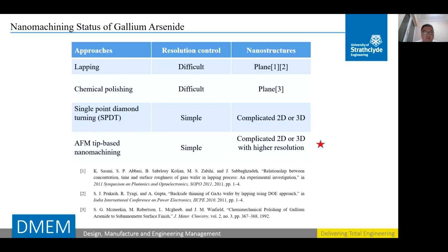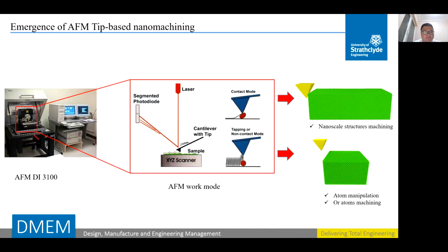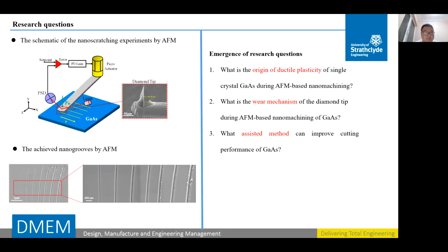So in this work, I use the AFM-based nanomachining method. On this page, AFM has three working modes: contact mode, tapping mode, and non-contact mode. In my work, I use the contact mode to carry out nanoscratching experiments on the gallium arsenide workpiece. Tapping mode and non-contact mode can be used for imaging. Here is the schematic of nanomachining experiments by AFM and the achieved nanogrooves.